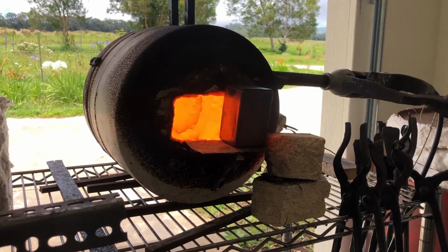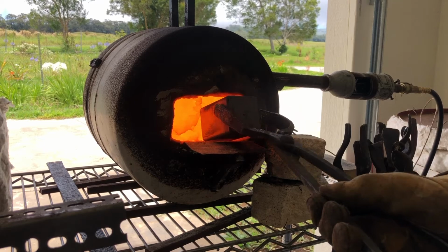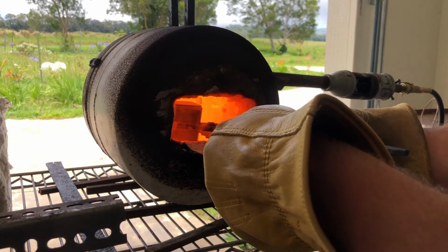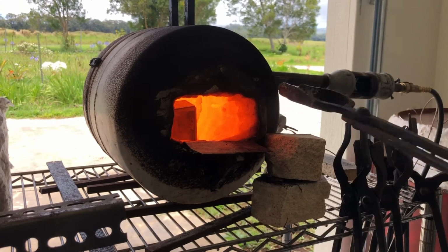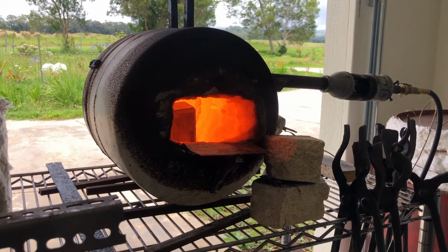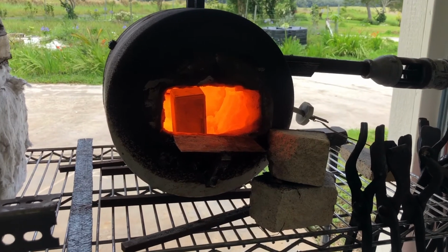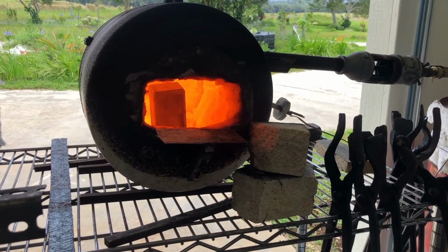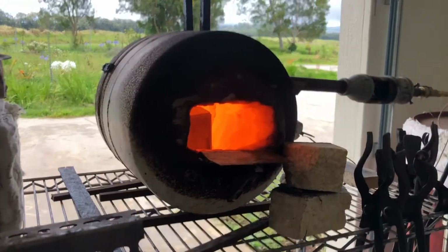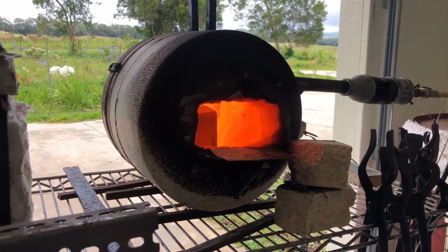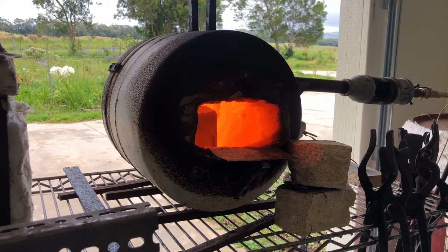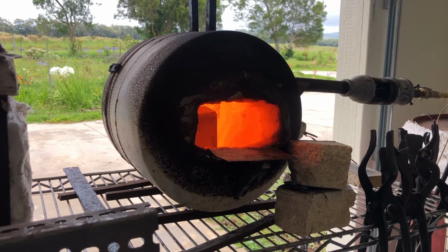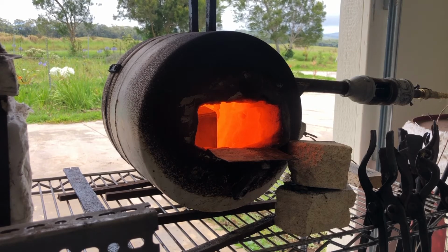But I'm going to go ahead and pop this in. Just want to make sure that it is sitting upright in there, sitting vertically. You can see I'm not getting some gigantic spurt of powder out the top, so we're in good shape. So now I just bring the temperature back up to sintering temperature of 1200 centigrade or 2200 Fahrenheit, and let it soak for a little bit, about 10 minutes, and we'll be ready to press.